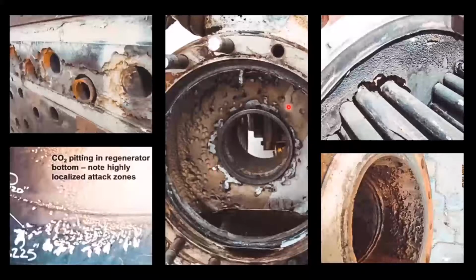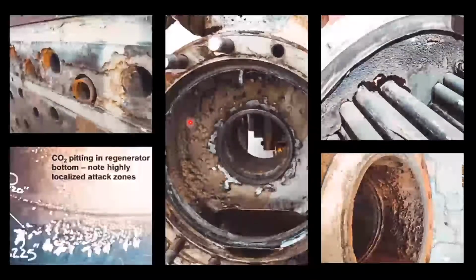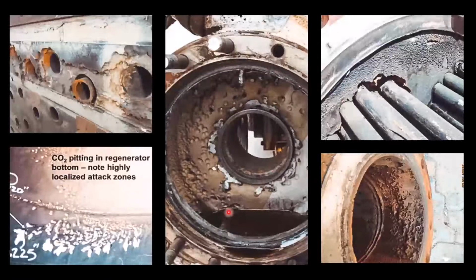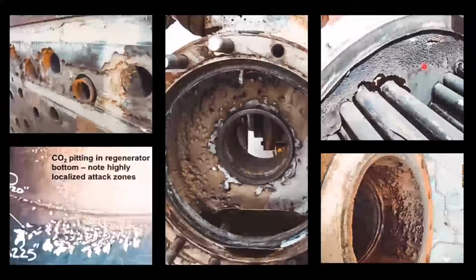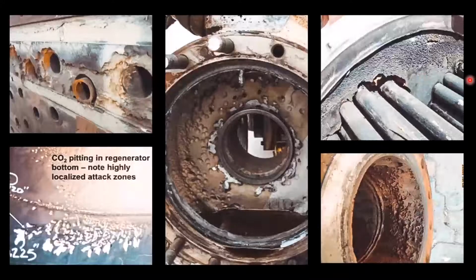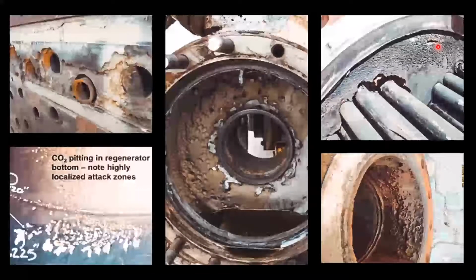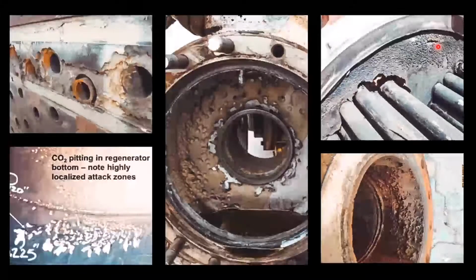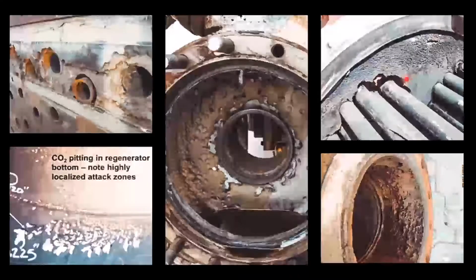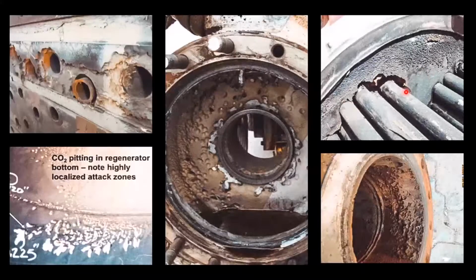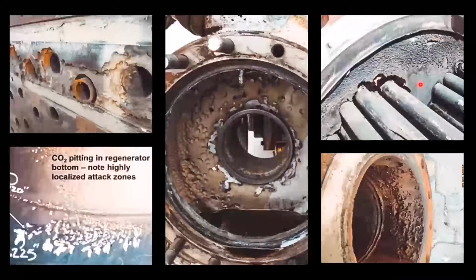And how do I recognize a CO2 pit? Here are some classic CO2 pits. They're sharp-edged, round-bottom pits. So this is classic CO2 attack on the head of a reboiler. This is the reboiler bundle. This plant decided they were overstripping their solution and they were going to leave more H2S to build a protective film on the lean side. The problem with leaving more H2S in the lean is that you also leave much more CO2. So they left more H2S, but not enough to provide a protective film, and all the extra CO2 that they left in the amine hit the reboiler and chewed up the reboiler bundle. So this was a catastrophe caused by poor decision-making on overstripping a solvent.